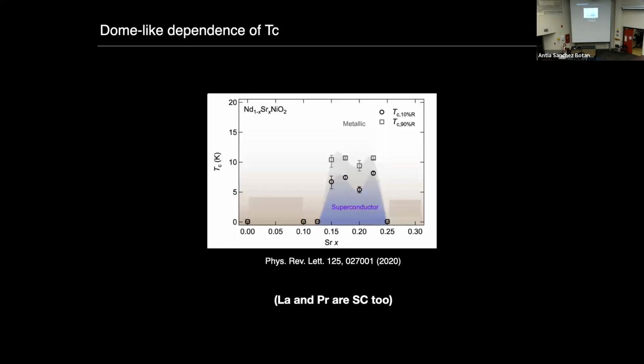So that was the original paper, but throughout these past 3 years, people have worked quite hard on this. And we now know that also the lanthanum and praseodymium analogs of these infinite layer materials are superconducting as well. And we also have a wide range of doping dependencies that show that we have a cuprate-like dome in these materials as well for the dependence of Tc.